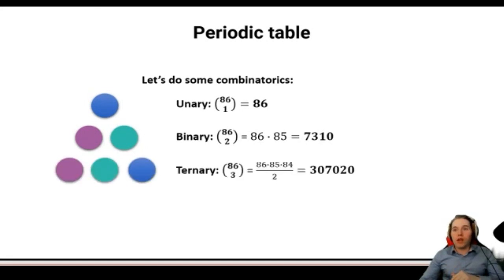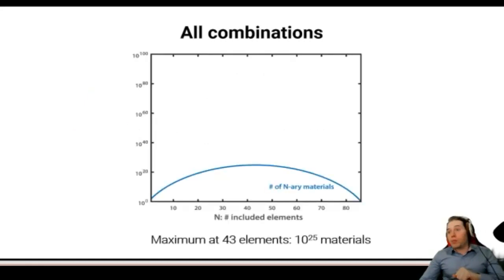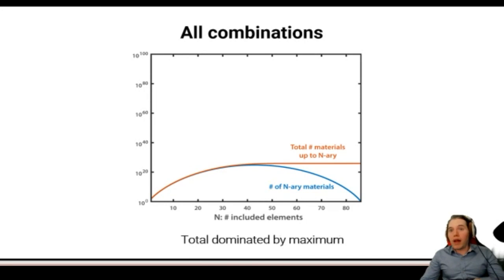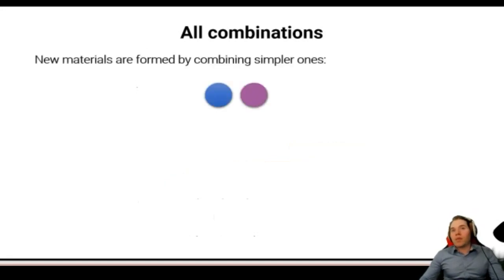If we then go to 3, we already have 300,000 combinations, and it keeps going like this. So if we put this on a graph, you see here that the most materials should be made out of 43 elements, and that there should be around 10 to the 25th materials of this kind. If we then add up all elements, we see that pretty much all materials in the universe should be made up out of 43 elements. Now, I've never seen a material with 43 elements, which means that we are probably making some kind of reasoning mistake here. And the reasoning mistake is the following.